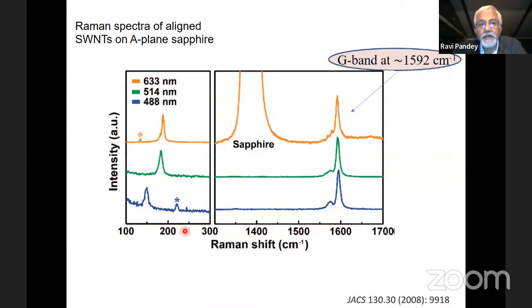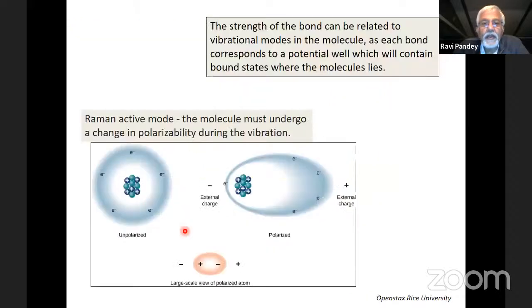How do we know how good these nanotubes are? The typical thing we use is called Raman spectra. This slide tells you that we are looking at the strength of the bond between carbon atoms in a given material by vibrational modes, because these systems are at room temperature. The bonds are going to vibrate. In terms of quantum mechanics, each bond corresponds to a potential well where the molecule lies. From there, you can determine the so-called Raman active mode, which is directly related to the polarization, the flexibility of the electronic cloud in the system.